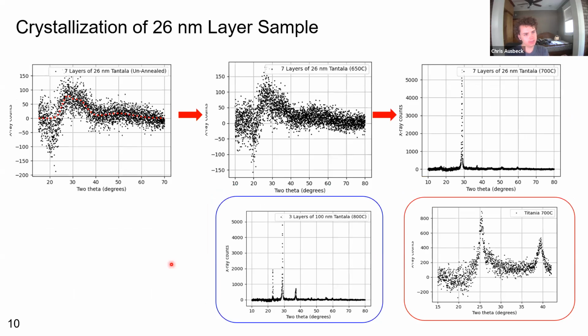So this is our thickest sample. This is the 26 nanometer layer sample. This is 7 layers. This one is a bit different from the others in that it's unannealed, and it's not crystallized yet. We bake it all the way up to 650 C, and it still hasn't crystallized. However, once we get to 700 C, it immediately crystallizes very drastically.